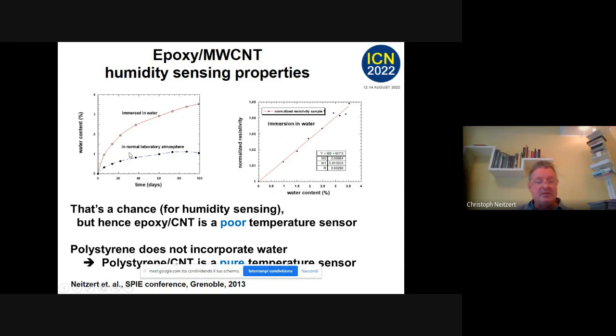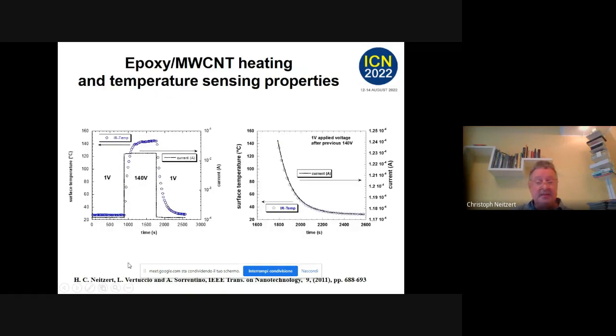And this is if we do it for a long time in laboratory atmosphere. We see also uptake of water until it saturates. And we saw then changes of resistance, but it's very slow because it's a very big sample. So that's a chance for humidity sensing, but hence epoxy is a poor temperature sensor. Polystyrene does not incorporate water. Polystyrene is a pure temperature sensor, just pure, because it does not take on humidity.